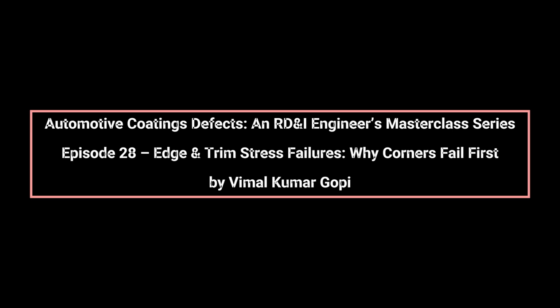From a troubleshooting perspective, OEM engineers first assess film build, application consistency, curing profiles, and additive distribution. Edge and trim failures are rarely due to a single layer. They are the result of compounded factors across the primer, base coat, and clear coat stack. Adjusting one layer without considering the others often shifts the failure point rather than eliminating it.